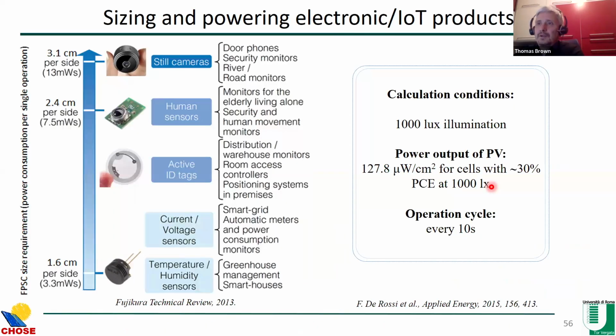And we did a calculation based on some Fujikura technical review data. And at 1,000 lux illumination with cells with 30% efficiency, you can think of developing a temperature humidity sensor just with a module of 1.6 centimeter per side. Human sensors, you need 2.4 centimeter. These are proximity sensors. Or you can take an image every 10 seconds with a still camera with 3.1 centimeter per side. So the bigger the device, or the more efficient the device, the more products you can operate.